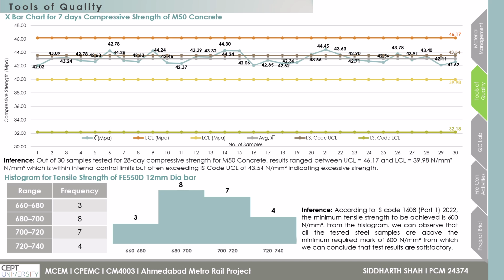Coming on to the histogram for tensile strength of 550D 12 mm TMT bar, we got this data from the external testing agency, and the frequency for different results is shown here. According to IS code 1608 Part 1 2022, the minimum tensile strength to be achieved is 600 Newton per mm square. From the histogram, we can observe that all the tested steel samples are above the minimum required mark of 600 Newton per mm square, from which we can conclude that the test results are satisfactory.